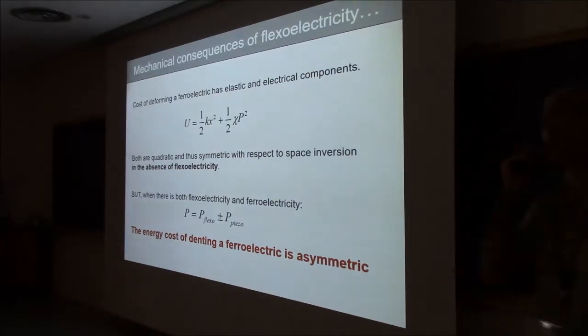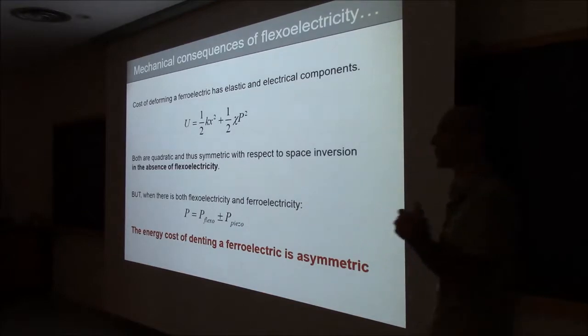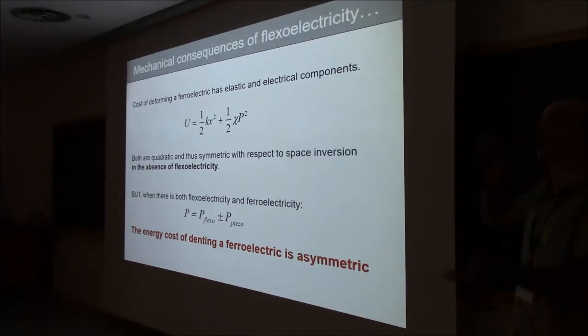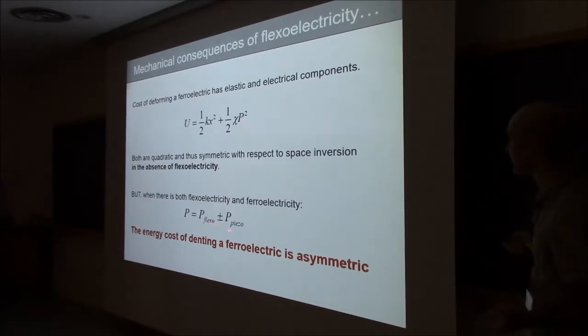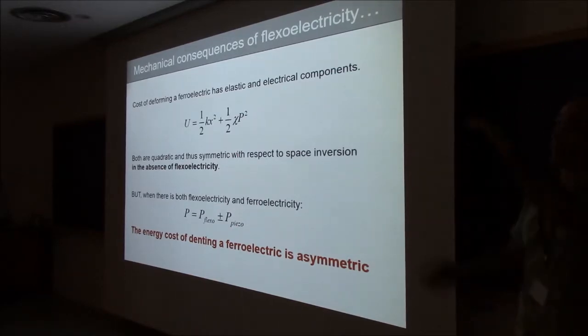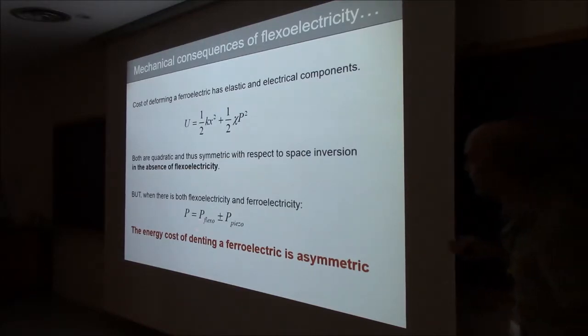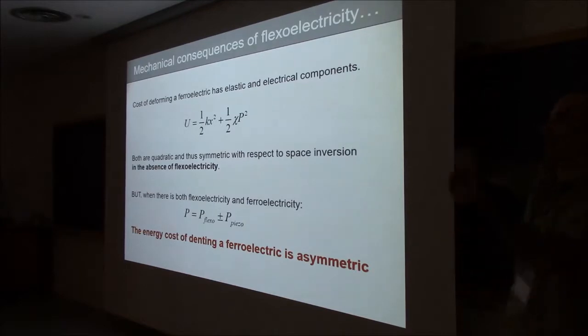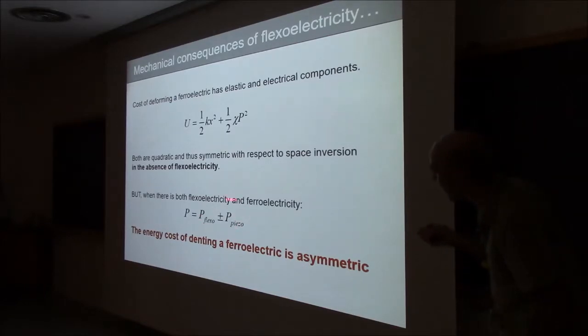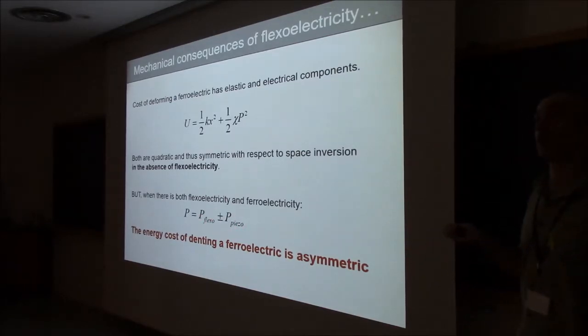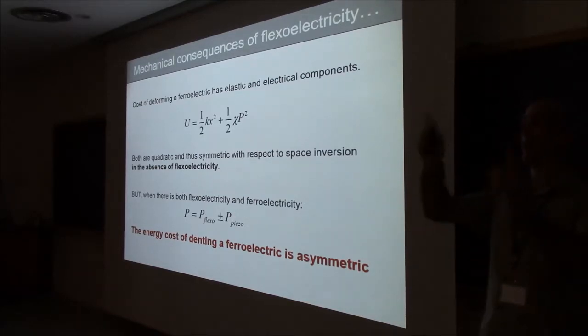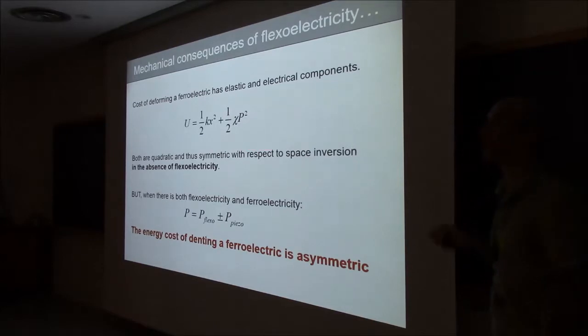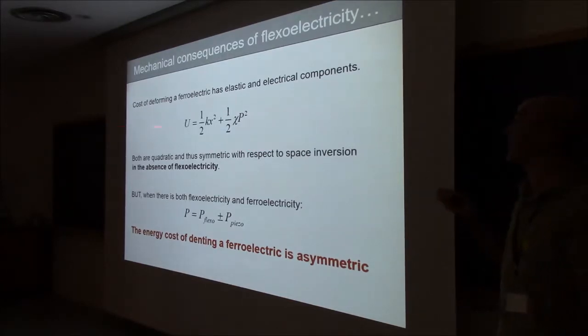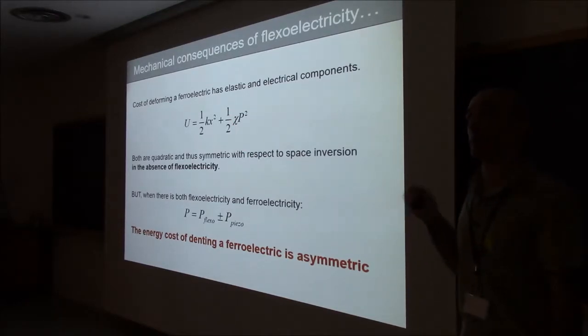But if you have flexoelectricity, so if your deformation is inhomogeneous, then your ferroelectric material will have two sources of polarization when you deform it. One given by the piezoelectricity, and that depends on the orientation, it depends on the polarity of your ferroelectric, and one given by the flexoelectricity, and this only depends on the direction of the strain gradient. It does not depend on the polarity of your ferroelectric. That means that these two contributions can be additive or subtractive, which means that the total polarization can be big or small depending on the ferroelectric orientation, and so P squared will also be big or small. So I have not changed the sign, but I have changed the magnitude of the total polarization and therefore the energy cost of the deformation.